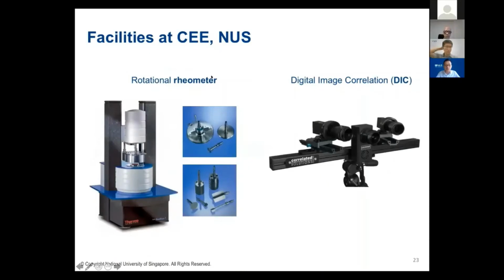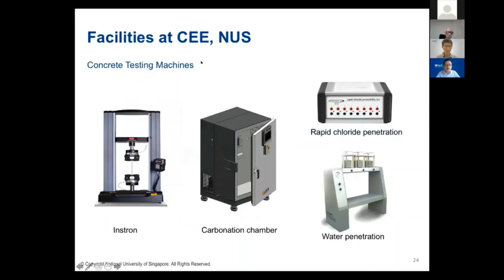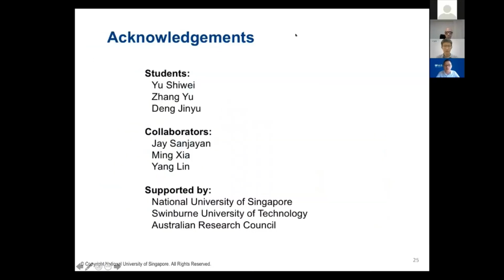In addition to the 3D printer, we also have a rotational rheometer, which is very important to design suitable printing concrete. There is another piece of equipment called digital image correlation, which helps us monitor the deformation during or after printing. Lastly, I would like to introduce a few standard concrete testing, high accuracy and high capacity instruments, and a carbonation chamber, rapid chloride penetration, and water penetration. This gives us the right instruments to characterize the printed product.